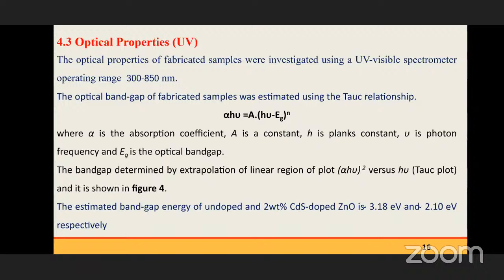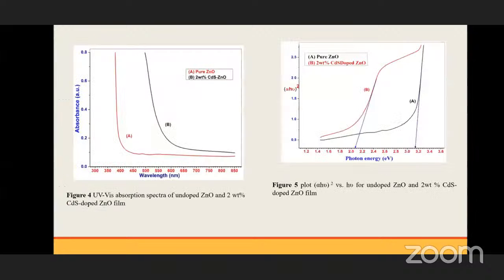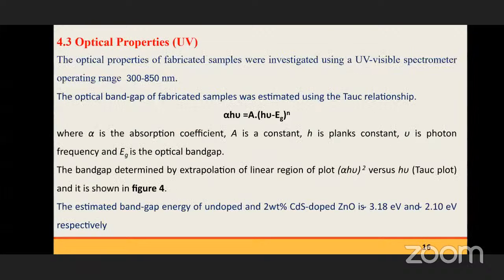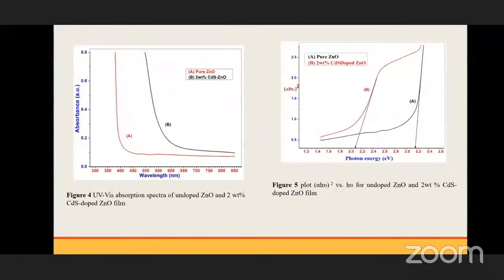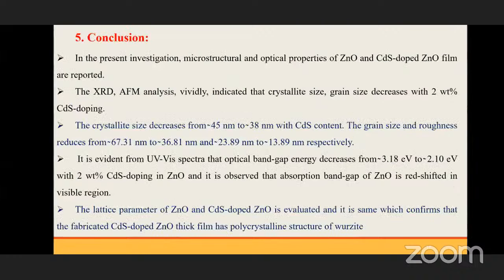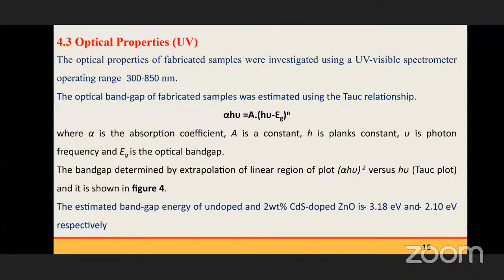Operating range 300 to 850 nanometer. The optical band gap of the fabricated sample was estimated using the Tauc relation. The band gap was determined by extrapolation of the linear region of alpha h nu squared versus h nu, and it is shown in this figure. UV visible absorption spectra of ZnO and 2% CdS doped ZnO, and here the linear extrapolation of the undoped and CdS doped ZnO. We found that the band gap of undoped ZnO is 3.18 electron volt, and with CdS doping 2.1 electron volt.